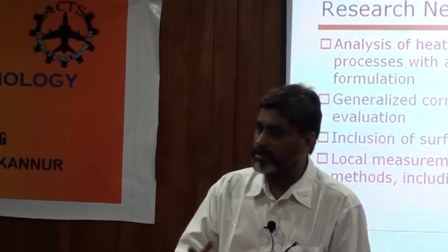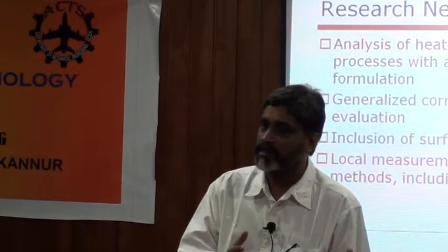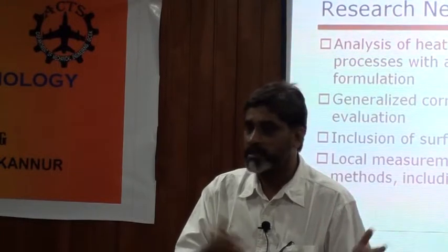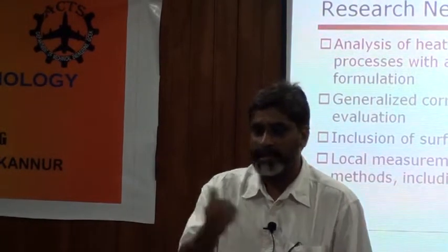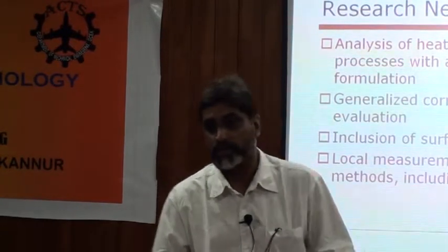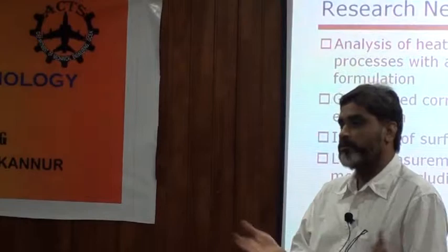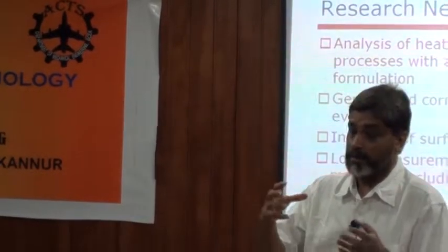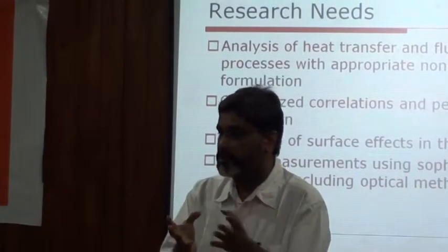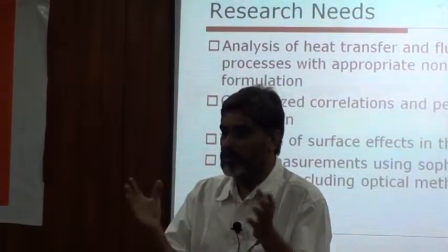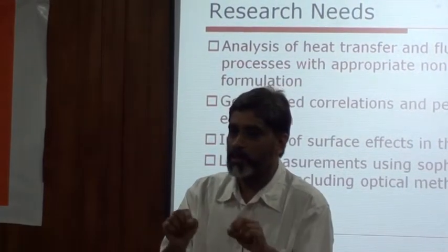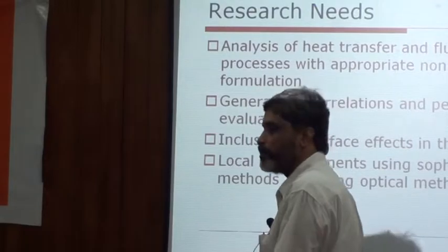Anyway, there is no question about the fact that the performance will be better if you include metallic oxide nanoparticles into liquids, because thermal conductivity will be increased quite a lot. He was telling about the thermal conductivity fact. So nanoparticle addition definitely is going to improve thermal conductivity, but you have to address the other problems like clogging, agglomeration, sticking together, because the particles are there. They have tremendous surface area to volume ratio. So a lot of surface energy, they stick together and maybe sediment down, the channels are blocked. So these kinds of things have to be overcome.